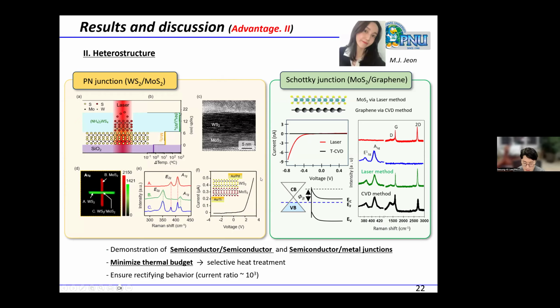Currently, I also study the origin of that. Firstly, from this SEM image, I can explain. When I synthesize MoS2 using this system, the crystal follows the surface of the bottom layer. As you can see here, the crystal is not cross-linked. It makes this kind of flat crystal structure. So I can say that using this method, we can synthesize a flat MoS2 film.